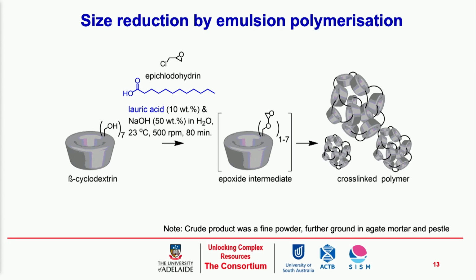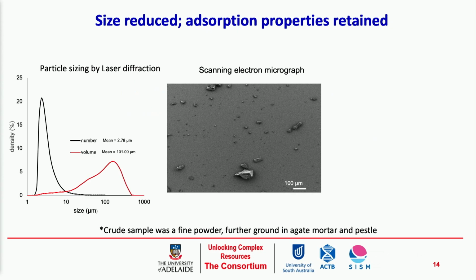So the next step here was to try and reduce the size of these particles a little bit. So I've introduced an emulsifying agent, being lauric acid, into my synthesis here, and was able to form it as more of a particle suspension. So rather than getting a big block at the end of it, I got a collection of fine powder. Again, some of these are still approaching sizes that are a little bit large, but for the most part, we